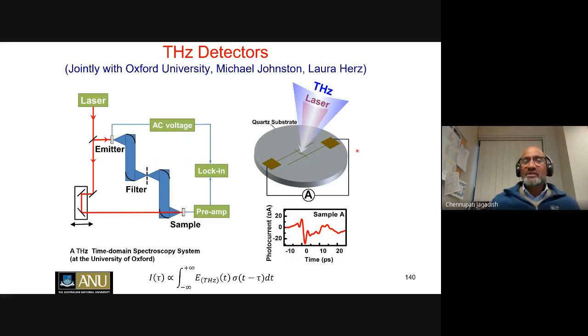And so thereby you're able to shine light, excite this with a laser pulse, and create electron-hole pairs, and come up with a terahertz pulse. The electric field of the terahertz pulse is separating the carriers between the two contacts. You measure photocurrent as a function of time. You see the time scales we are talking about are picoseconds. They're very good for terahertz applications, for example, terahertz detection. If you measure the current as a function of time, you can measure the electric field of the terahertz transient as a photoconductive detector, for example. Also, you can measure the time-dependent photoconductivity of the detection material as well.